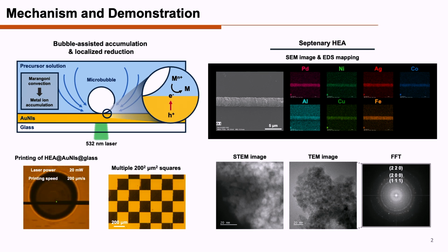And because of the surface tension gradient and the temperature gradient induced by these photothermal effects, it can generate a Marangoni convection flow to guide the metal ions in the solution to the region below the bubble. So it causes a metal ion accumulation effect. And also, because of the light irradiation, it can induce a localized reduction effect, like the hot electrons from the plasmonic substrate will induce the reduction of metal ions here. So with these two effects, we can successfully synthesize high entropy alloys, just like this video shows. Yeah, and here's the pattern we try to print.